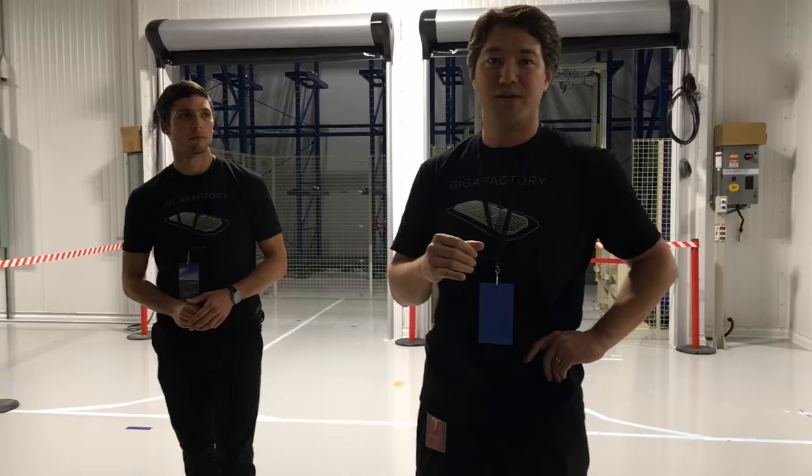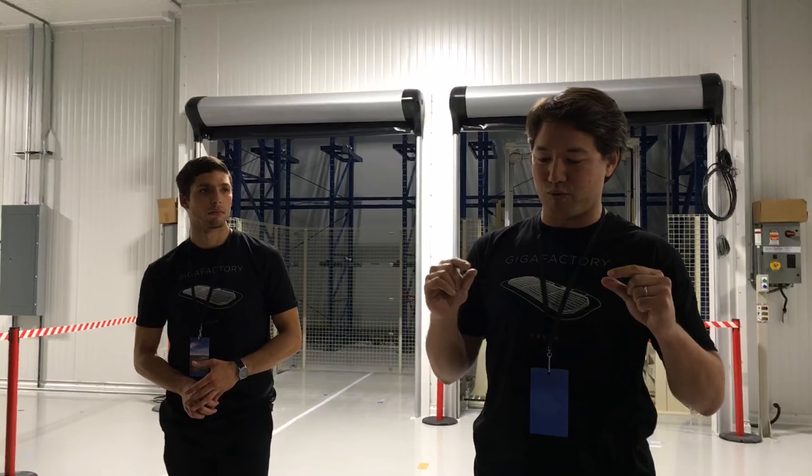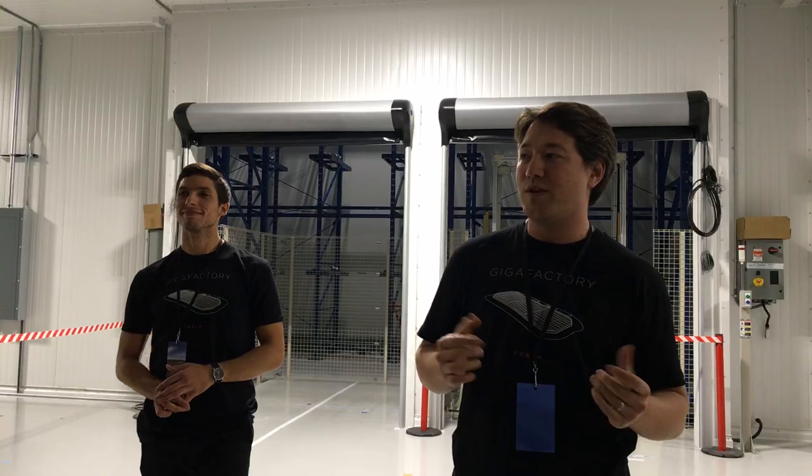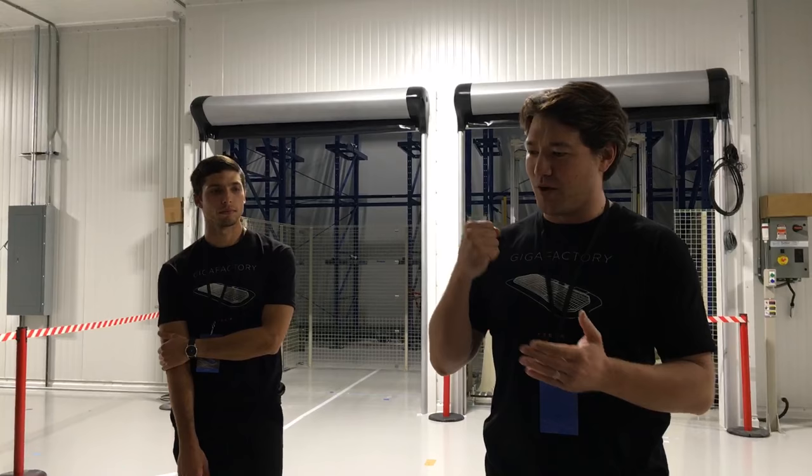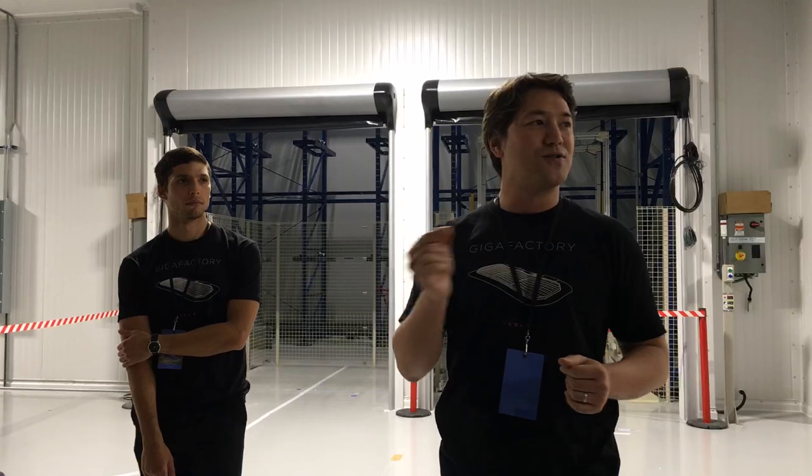So what we're trying to do now is get rid of the air that is in the place of where the solvent was, basically. So what we're doing is compressing that material down to a really, really specific and precise thickness, and that's roughly the diameter of a human hair. And really what we're after is a target porosity in the material after compression. We're trying to strike that really fine balance, and just to give you an idea for what we're after, if you compress this material too much, you're actually interfering with the flow of the lithium ions going into and out of the electrode material.